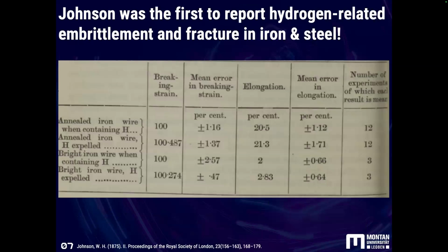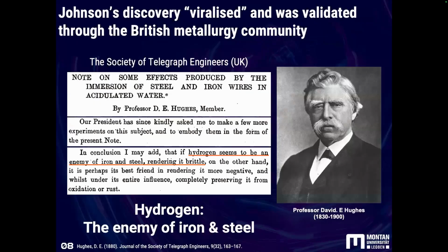But Johnson was the discoverer of the hydrogen embrittlement effect because he measured the elongation before and after the hydrogen action. So when containing hydrogen, the iron wire had a certain elongation, and then when he expelled the hydrogen by annealing, the elongation increased. So he measured the mechanical properties. So he was the discoverer.